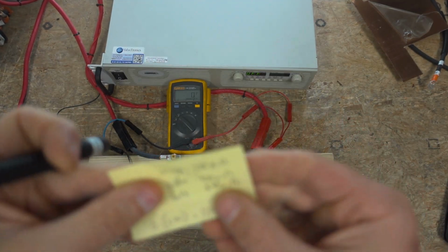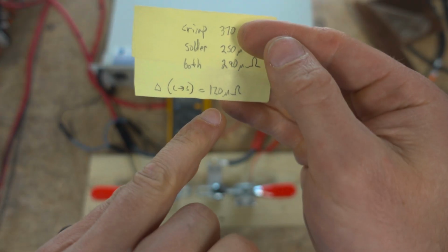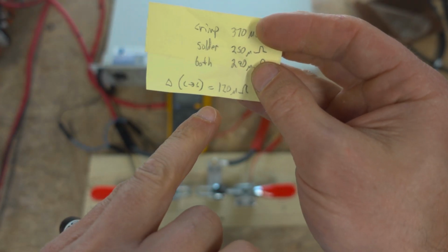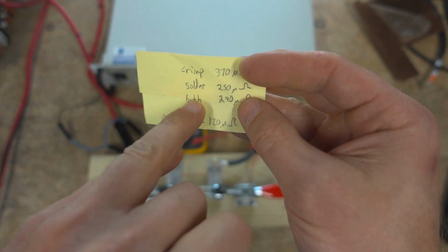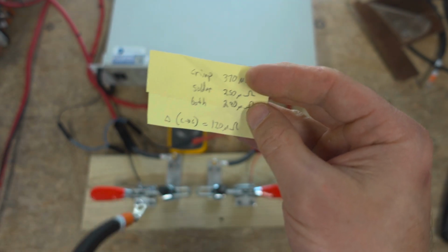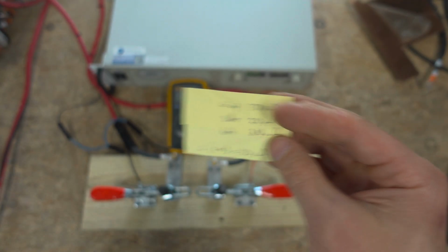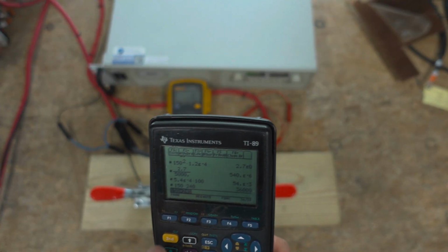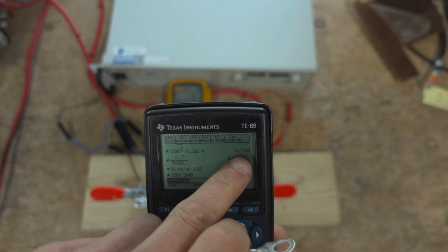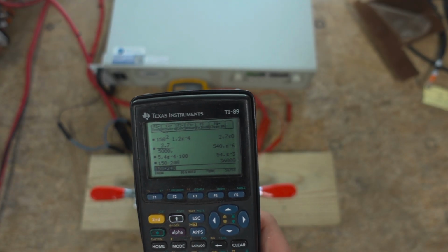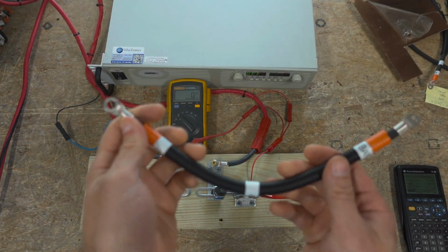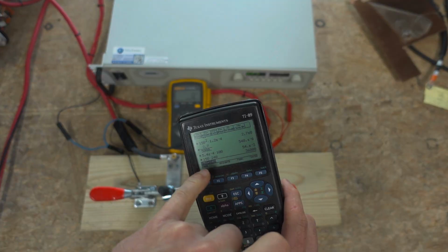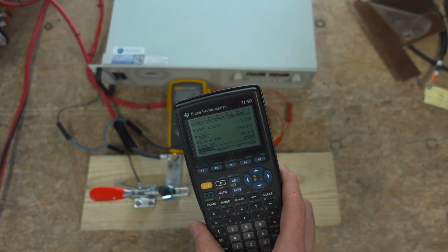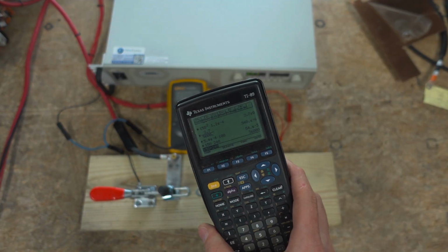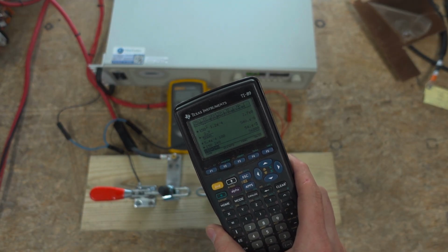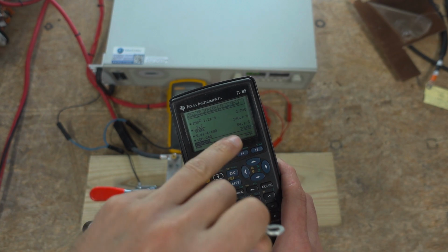So I want to note too, the delta here is actually quite small. It's 120 microohms between crimping and soldering. So soldering in that test was 120 microohms better. But if you look at 150 amps, you're talking about 2.7 watts of additional power in a cable like this. When you're pushing, say, 150 amps at 240 volts, you're pushing 36,000 watts. So 2.7 watts is nothing, especially compared to the amount of internal heat loss you're going to have from the chemical resistance of the battery cell.